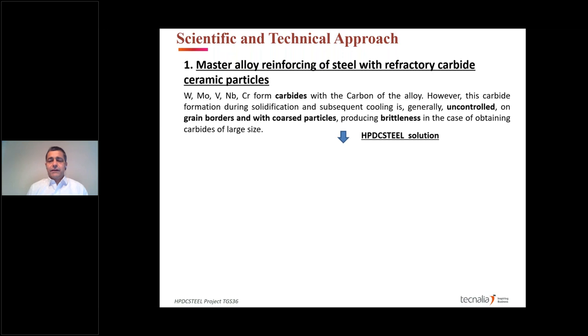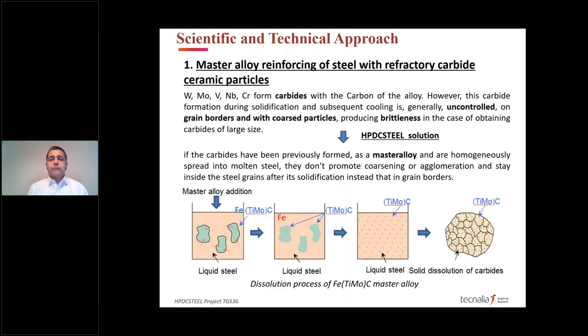So what is the strategy of this project? We are focusing on trying to introduce carbides into the steel matrix, but we know that normally if we introduce these carbides, they can be not well distributed, they can agglomerate, they can give brittleness to the material. So we thought about the possibility of introducing a master alloy, where this master alloy is an iron that contains titanium molybdenum carbides. When we introduce this iron with distributed titanium molybdenum carbides into the steel, we can have a good dissolution of these carbides because they are probably welded with the iron. So this is the concept.